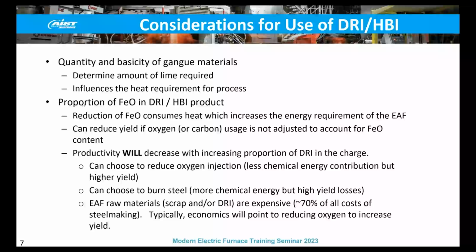Proportion of FeO in DRI, or FeO in DRI HBI product—the reduction of FeO in electric arc furnaces consumes a significant amount of energy. He uses the term heat. It can reduce yield. So as you add fluxes to the electric arc furnace, imagine that as basically a big sponge, and pretend it's somewhere between 33 and 37% FeO by weight.